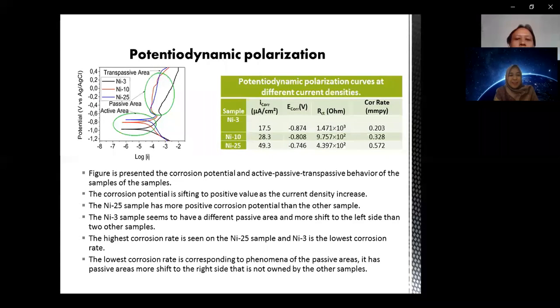The corrosion potential shifts more to positive values as the current density increases. The nickel 25 sample has a more positive corrosion potential than the other samples. The nickel 3 sample seems to have a different passive area and shifts more to the left side than the other samples. The highest corrosion rate is seen on the nickel 25 sample, and nickel 3 has the lowest corrosion rate. The lowest corrosion rate corresponds to the passive area phenomenon. It has a passive area shifted more to the right side that is not owned by the other samples.